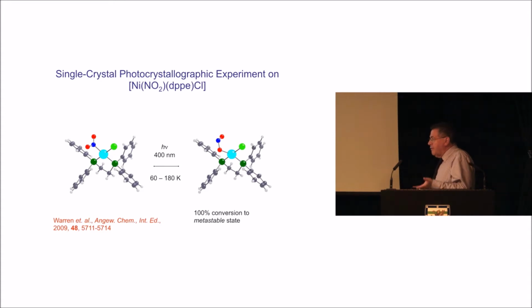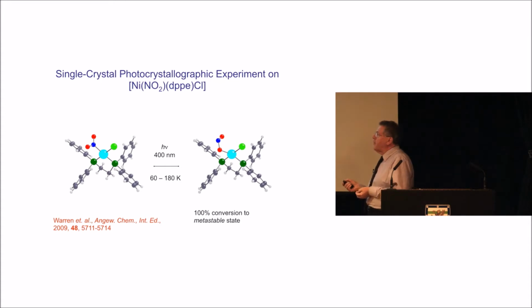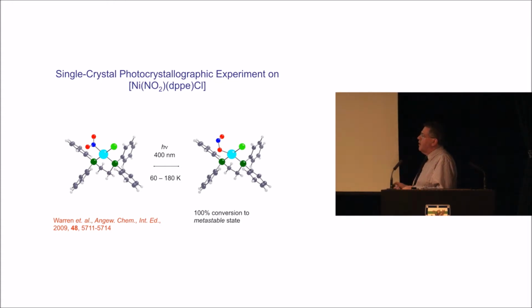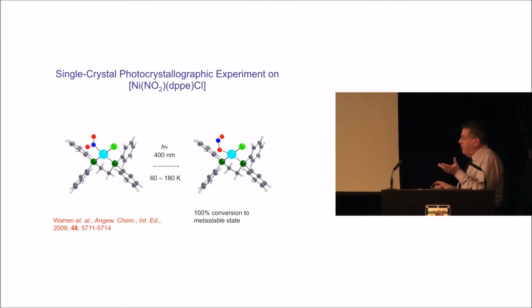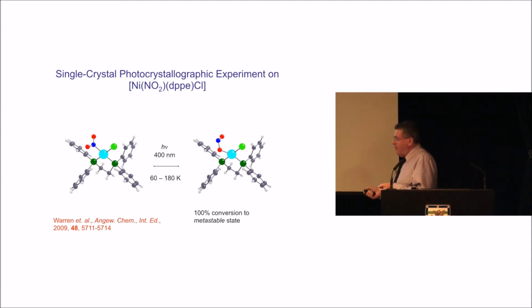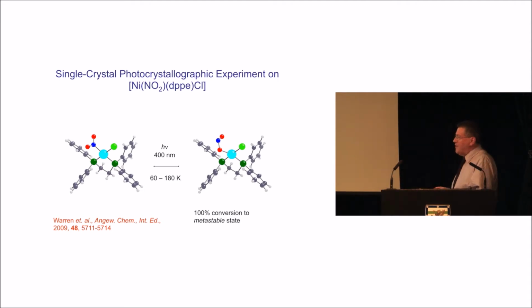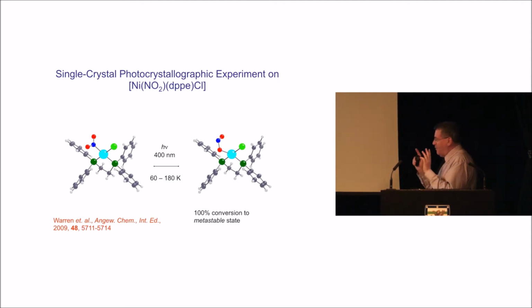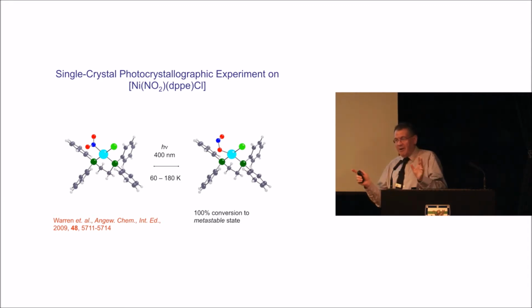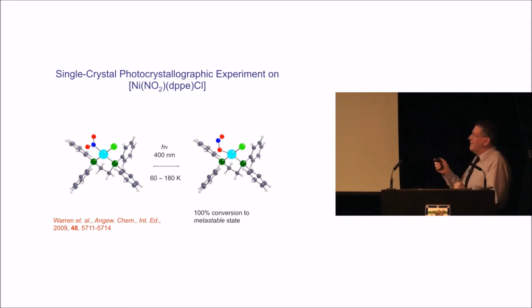Does it happen in a single crystal? And the answer is yes. In this system with 400 nanometer light between 60 and 180 K, this goes through to 100% conversion. So it's the first system that actually does 100%. So technically we now have some sort of counting mechanism where that might count as a binary 0 and that might count as a 1 in some sort of molecular computing, usually left for EPSRC applications rather than audiences of this caliber.